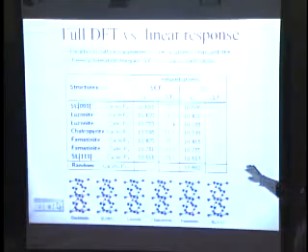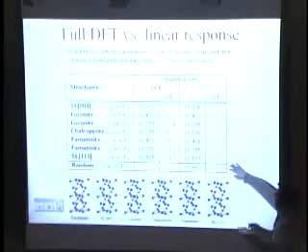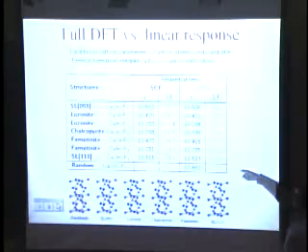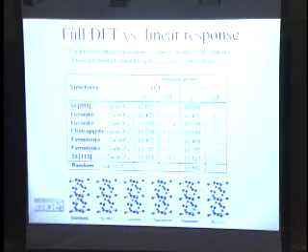And as you move around, you see that there are cases in which the error is larger, 4 milli-electron volt, and 4 milli-electron volt is very small, but it's still 10% of this mixing free energy. So it's somehow relevant, but I would say we still do very well.